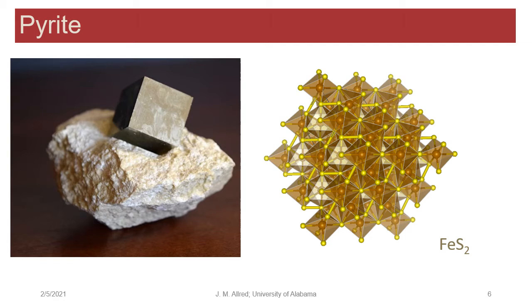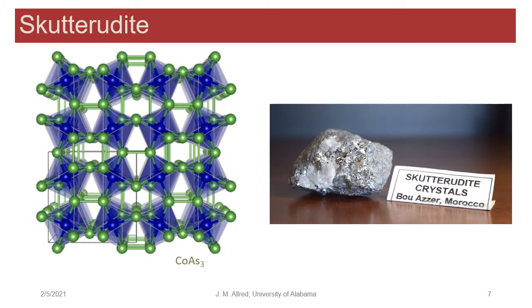This is just a nice example because we can exploit these kinds of ideas when we want to design structures. Here's another one that does a similar thing. It's not pyrite, it's skutterudite. It's got a cooler name than pyrite. And you've got squares of arsenic ions. And so same thing where you have to change how you count your electrons based on the bonds there are between those atoms. So homonuclear bonds are important when we think about structures like this.